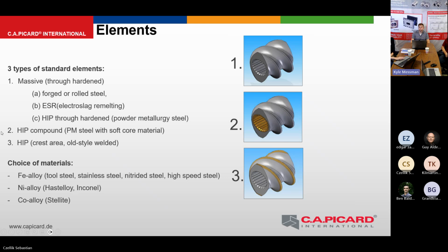Then we have our HIP compound, which is a PM steel with a soft core material. I will tell you on the next slide why you should choose, or why we have big advantages when we have a soft core. And then we have the HIP crest area. That is only for very special applications. If someone needs like a bearing effect, we can use them as stellite or cobalt-based material. Or if people have very corrosive environments and need a nickel material, then we can make a nickel crest that has better properties or higher hardness than the base material. Yeah, we can choose different types of material.